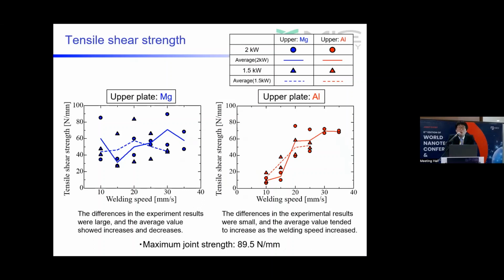A tensile shear test was performed to evaluate the strength of the joint. The test piece shape is a 50 millimeter wide rectangle. These figures show the effect of welding speed on tensile shear strength per 1 millimeter of welding length. The left-hand side shows magnesium as the upper plate by blue marks, and the right-hand side shows aluminum as the upper plate by red marks. The laser power of 2 kilowatts is indicated by circle marks, and 1.5 kilowatts by triangle marks.